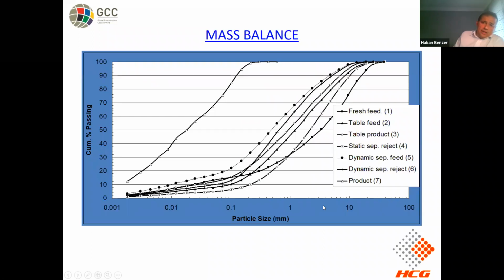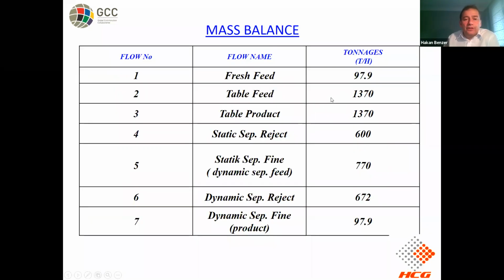And we stopped the mill, we got the samples, we mass balanced the circuit. You can see that this is the product coming out from the system, and the fresh feed coming into the system is here. So you can see that there is a very high circulation within the system because everything is occurring, and the grinding under the rolls is very small. Especially the reduction ratio of the grinding is not big. So this is the value of this equipment. Very high circulating load ratio can be achieved.